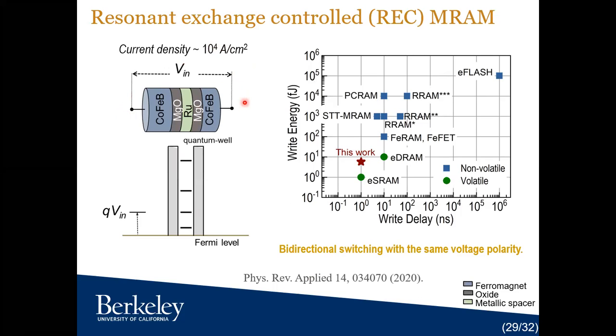Although this is a voltage control mechanism, we don't need current to switch it. But since this is a two-terminal device, when you apply a voltage, you also have a current. And the density is very small, where in STT it was around 10 to the power 7 amp per centimeter square. We can achieve 10 to the power 4 amp per centimeter square. And that translates into a much lower write energy because energy is I square R, proportional to I square R. And we expect this new type of device to be here. The energy, we are expecting it to be slightly lower than embedded DRAM, and the device can be as fast as SRAM.